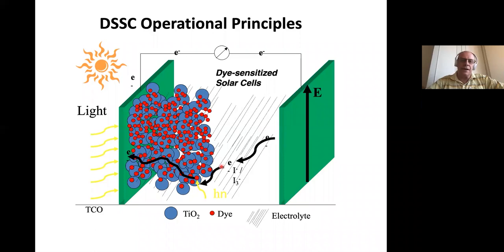So light comes in from this side normally, and then you excite the dye. So the dye is then injecting electrons into the TiO2. It goes through all these particles, and that was one of the huge mysteries in the early days, how this actually could happen that efficiently. And we extract it as a current and potential.